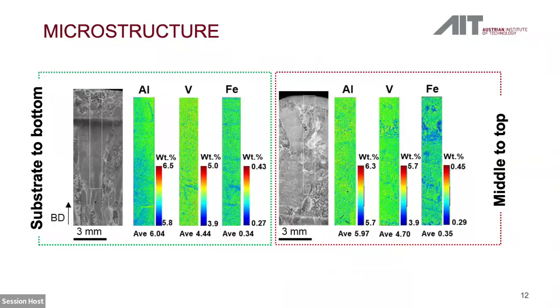A further interesting result is the local variation in chemical composition. If you think about the material being separated into a top section and a lower section, this is compared here. The lower portion of the material encounters this repetitive heat treatment, whereas the topmost layer does not. It's just deposited once. So what is seen here is that segregation occurs due to the solidification. But throughout the process and the repetitive reheating of the material, this segregation gets less and less.